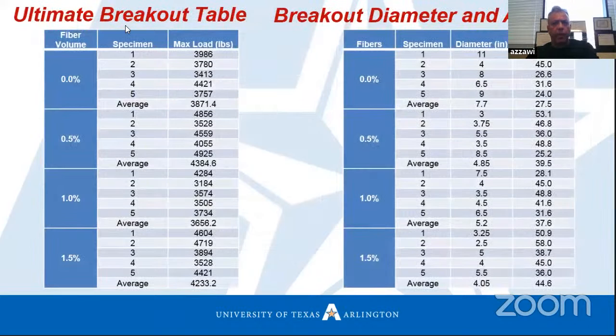And this table shows us the ultimate tensile breakout for different mixed design, and the other side shows us the diameter and the angle table. So as we see, with 0% fiber means we don't have any fiber. This is the angle, the average here, and the diameter we have is around 8 inches. If we increase the fibers, the diameter decrease, the angle increase of the concrete breakout, and also the load, as we see, is increased as the percent of fiber increased also.